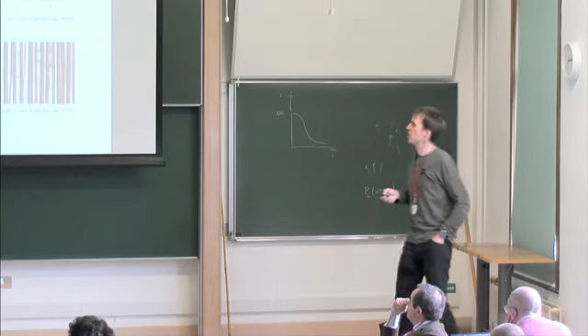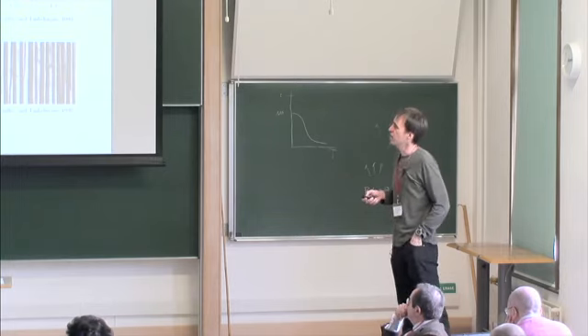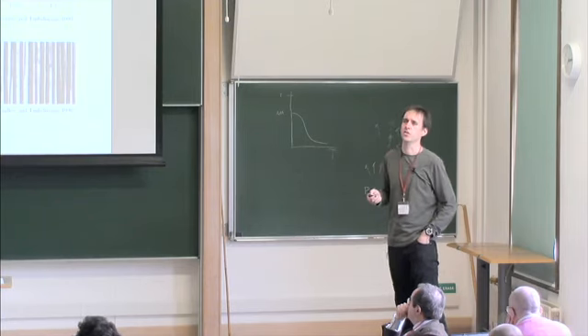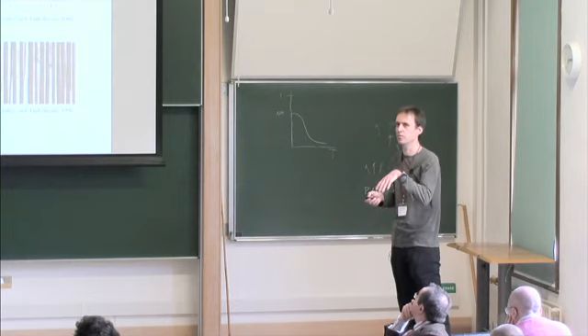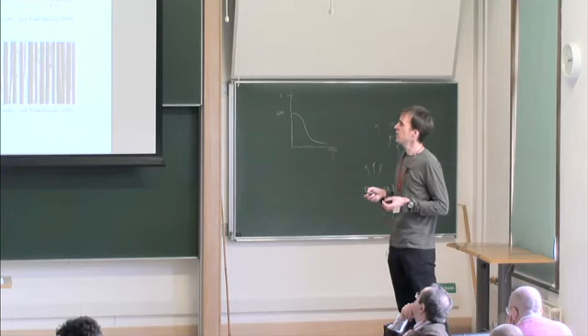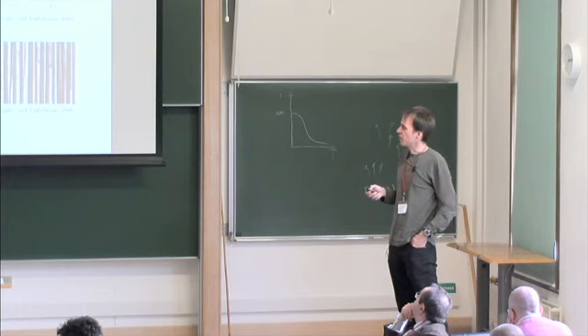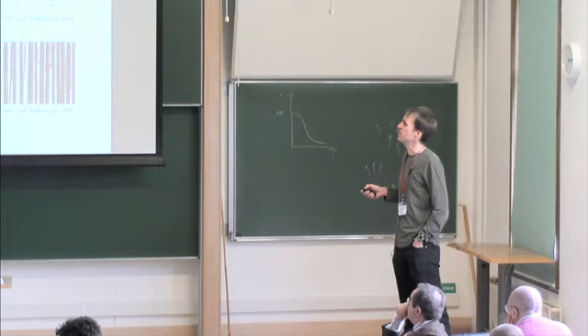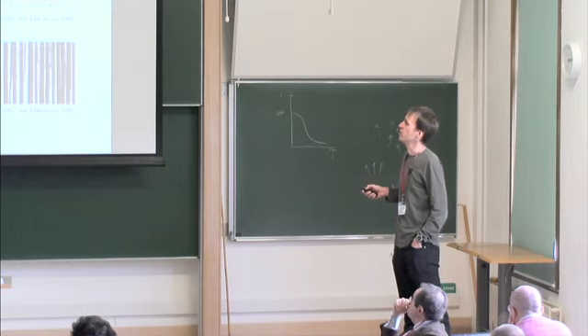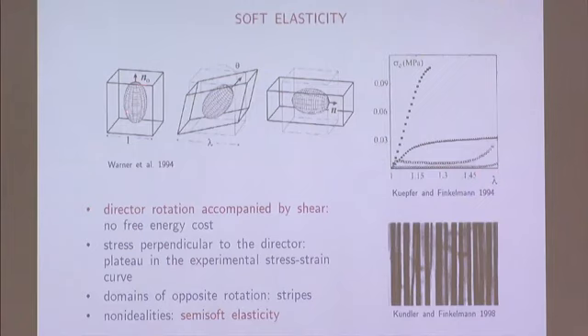So now the question is, can something like this happen also in a liquid crystal elastomer? It's not very obvious why this should be possible, because the nematic material is embedded in a polymer matrix. It turns out this can be done, provided that the rotation of the director is accompanied by a shear deformation. So this ellipsoid here corresponds to the distribution of end-to-end distances of polymer chains, and it is rotated without any change in shape. This is why there is no free energy cost in this case. And this is nicely predicted also by the so-called trace formula developed by Professor Warner and co-workers.